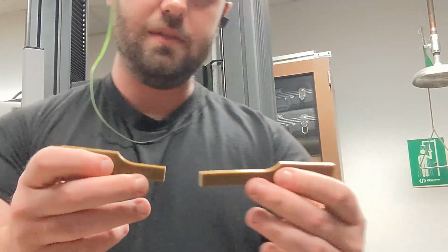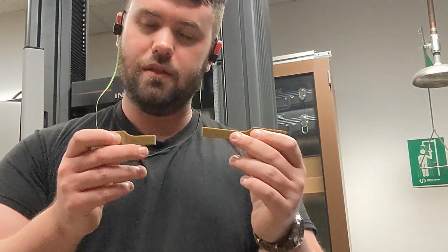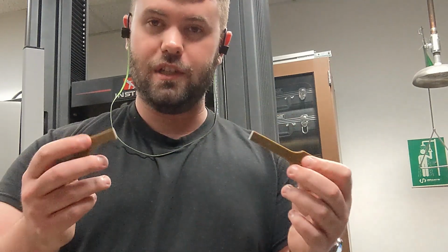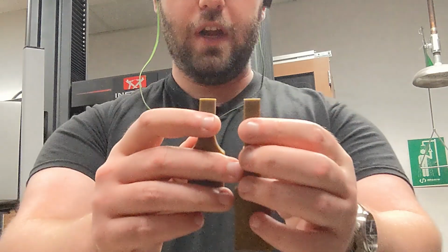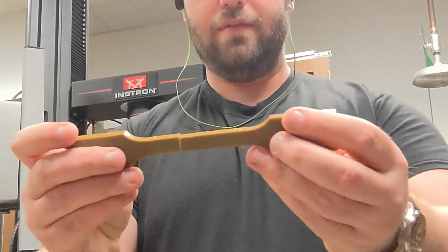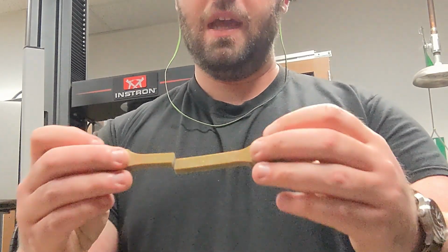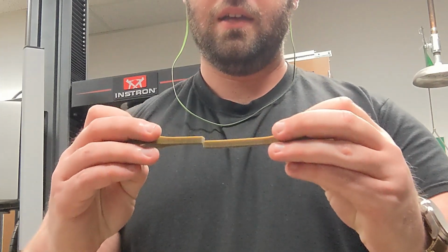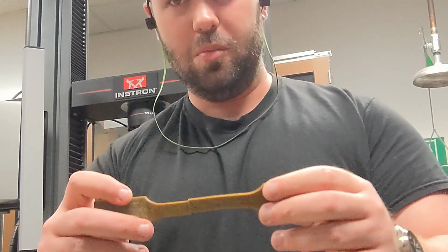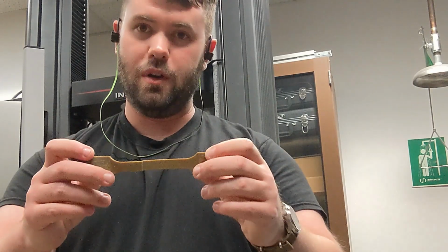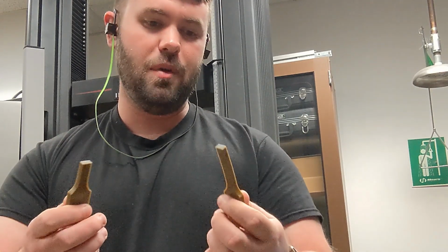So as soon as the amorphous chains got stretched enough where the crosslinks were the main thing holding it together, the crosslinks failed, and then the whole thing failed. So we got our nice brittle fracture surface, and maybe very, very little plastic deformation, maybe a tiny bit, but this is pretty close to what it was when we put it in there. It might be 10 millimeters longer.